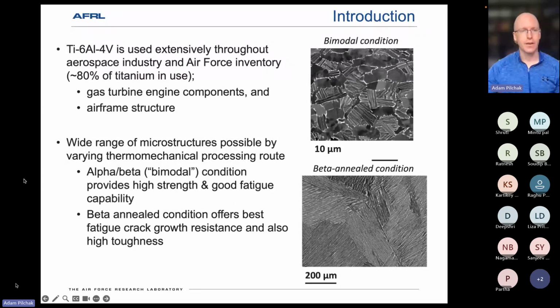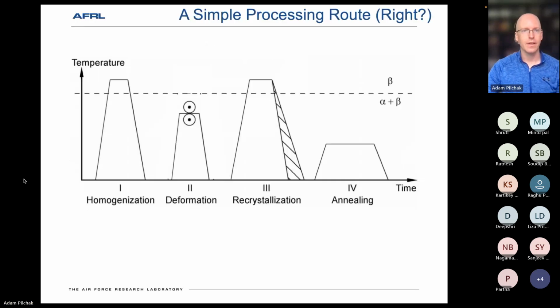And so many of the airframe components then utilize this beta annealing approach, where you can form relatively large colony-like microstructures, and they have the benefit of causing a lot of crack path or crack tip deflection, bifurcation, secondary cracking, and things, all of which reduce growth rates and contribute to the overall toughness.